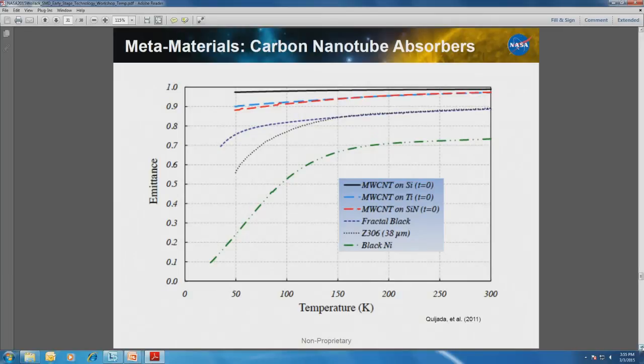And so one place you can use that behavior is for passive cooling. So these are various materials, and I'm not going to read them all, but the ones of particular interest are up here, and these are the carbon nanotubes. And they are pretty effective. The one challenge is, we do a lot of superconducting stuff, and the substrate material, the way they're bonded down, is magnetic, and we don't really like some of those materials, so we actually haven't integrated them into our sensors,